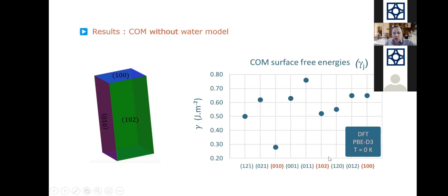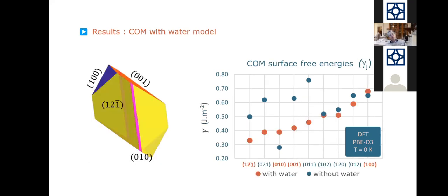We take out the most important ones, yes, and this is what we obtain when we are calculating without water. Without water, this is like growing crystals in space, yes. So this is not quite realistic. So then let's introduce the effect of water. Now, if we have the effect of water, we obtain the following graph, which is shown here with the orange big dots, and then we see that in fact the trend is changed. And if we use these surface energies with the formula of Gibbs-Wulff, then we obtain this morphology. The problem is, if you remember what we have seen before, that the morphologies were hexagonal platelets in kidney stones, and then something a little bit more three-dimensional in the quarries in nature as a mineral.